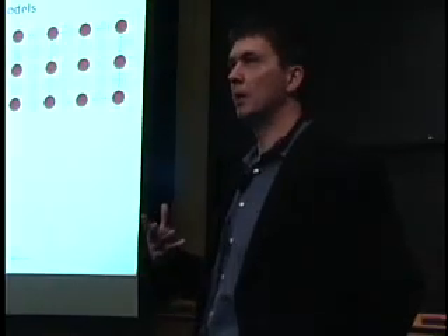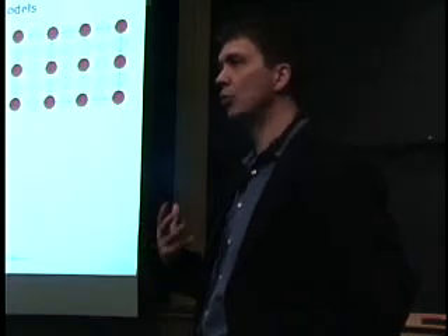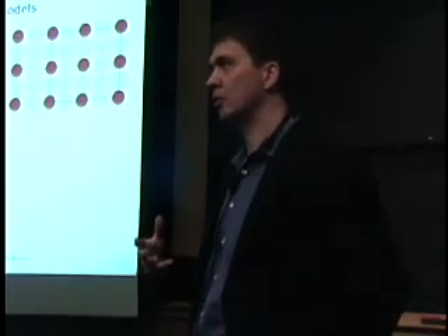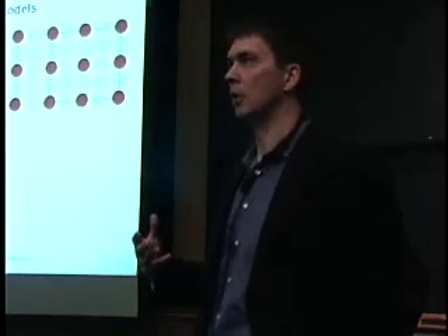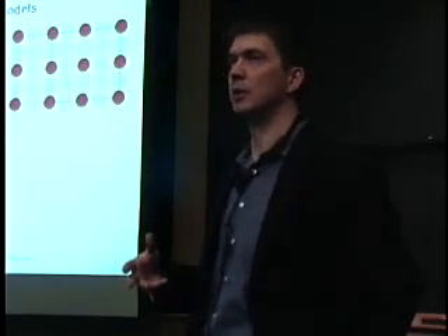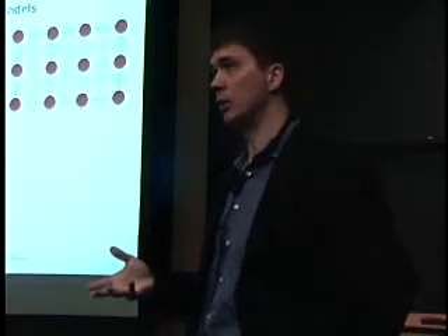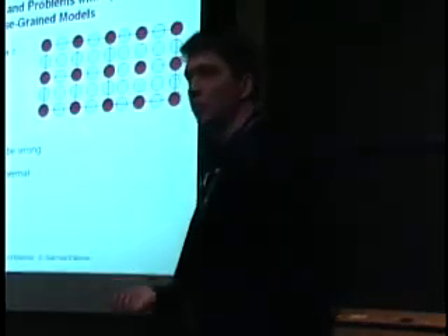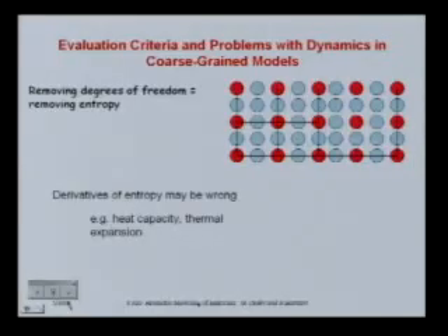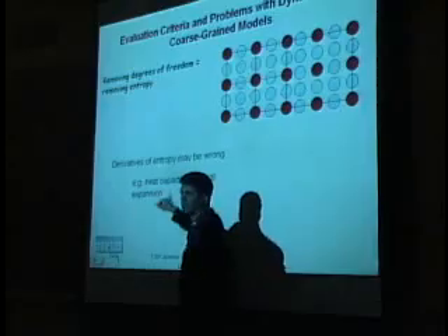You may not worry about that, but the problem is that if you do dynamics, your system will equilibrate along certain derivatives of the entropy, and you'll get them wrong. If you get the entropy wrong, you'll get its derivatives wrong. Some of the ones you may worry about are heat capacity, which is the temperature derivative of entropy, but also thermal expansion, which is the volume derivative of the entropy—you may worry a lot more about this if you do mechanical behavior.